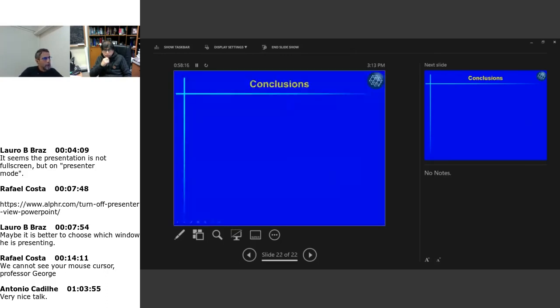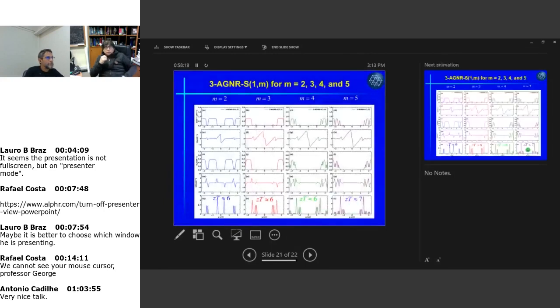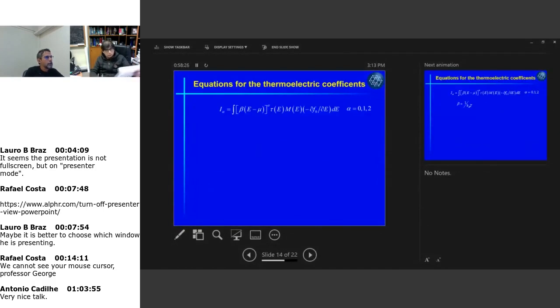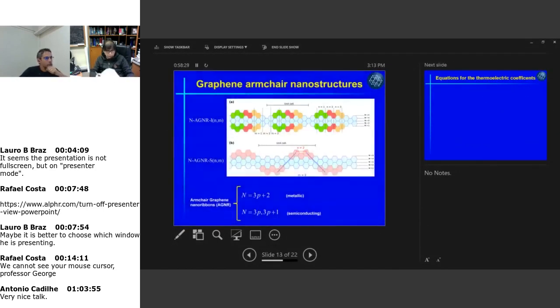So I should point out, maybe I should go back to this slide where I showed the nanostructures. I should point out that we didn't do the calculation of kappa lattice for the heterostructures. We just used the results we had for the pristine armchair graphene nanoribbons. We can reasonably expect that kappa L for the heterostructures is smaller, because you have these interfaces between these different regions here, and the phonons can scatter here.